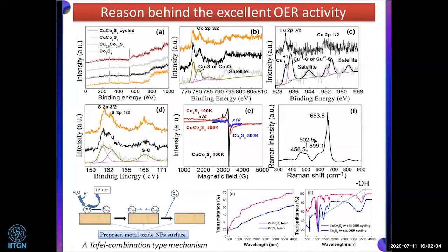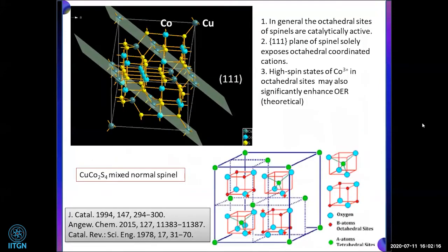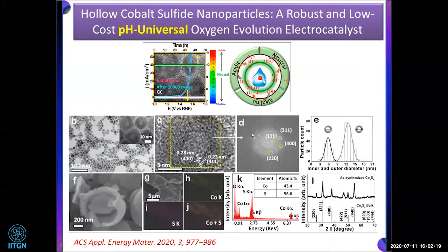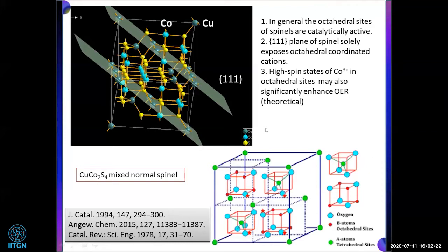And this is the Raman spectra. And now from this XPS and from EPR, and I'll come to the FTIR, what led us to the conclusion is, if you see this slide, what we generally know is that copper cobalt sulfide is a normal spinel, the octahedral sites are catalytically active, and 111 plane of the spinel solely exposes the octahedral coordination. So what we found from the XPS is that it is mainly cobalt 3 plus, and from EPR we found it is cobalt 3 plus in high spin. So our results are actually corroborating earlier theoretical results.